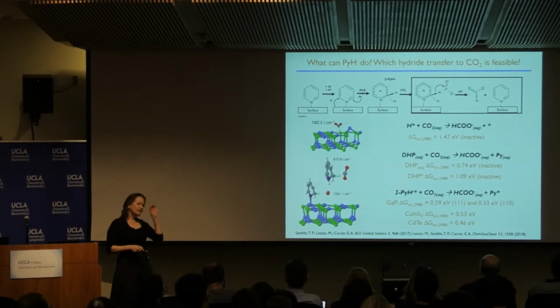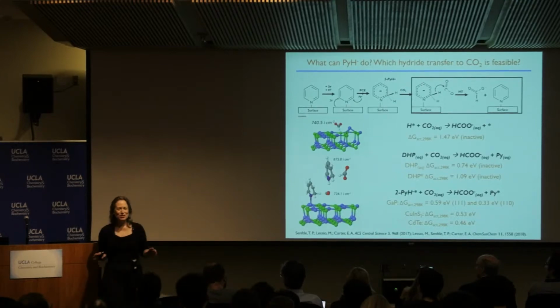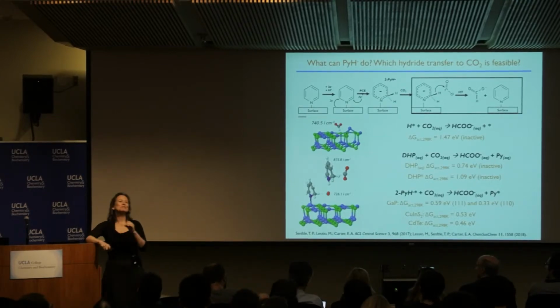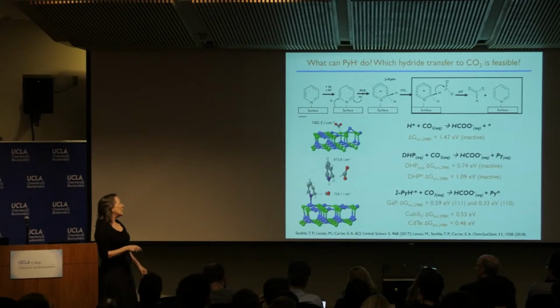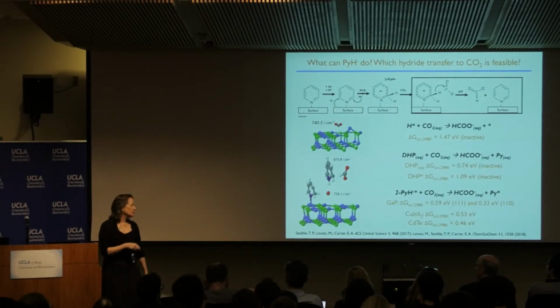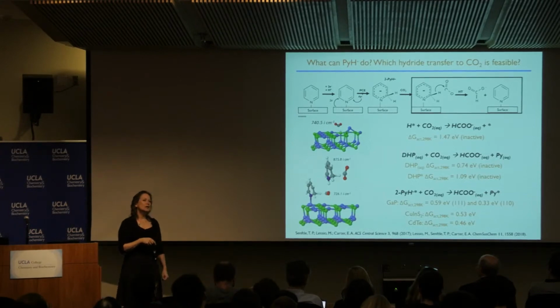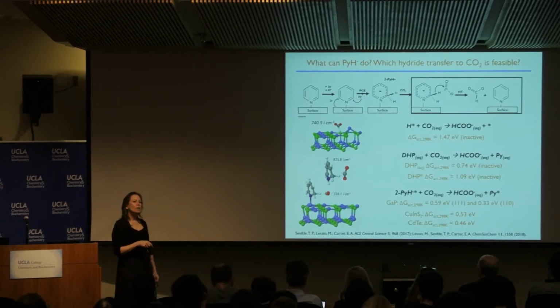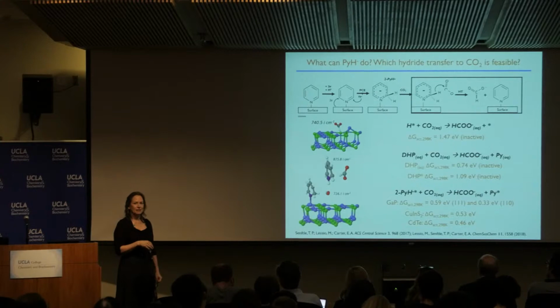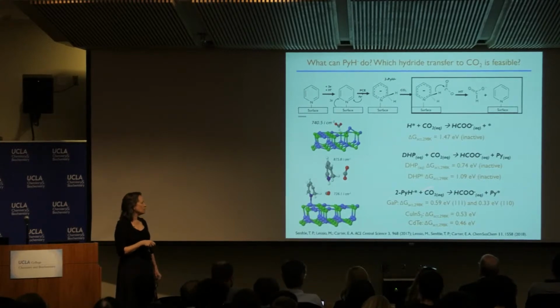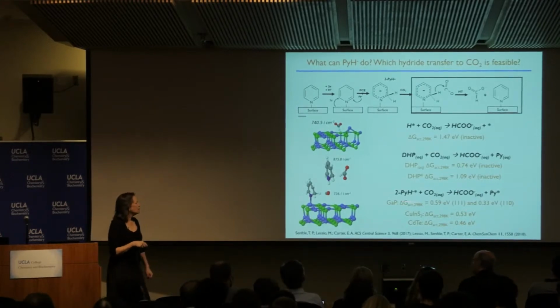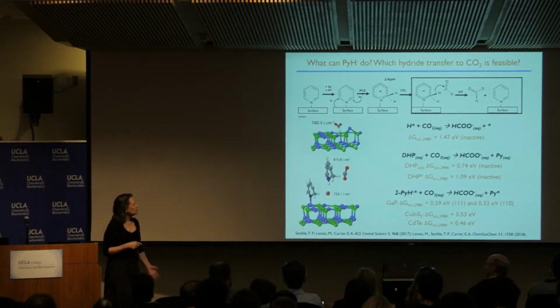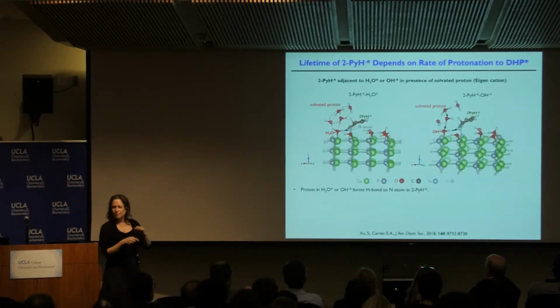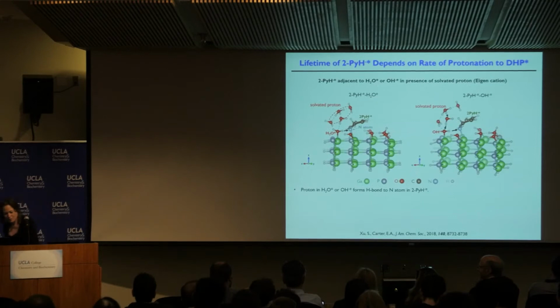And the beauty of that is that Andrew Bocarsly has frustratingly unpublished data. It's in a PhD thesis. We've been trying to get him to write it up with us. But the fact is that what they showed is that if you etch the gallium phosphide 111 crystal, you make facets of the 110, and the rate increases dramatically. So this is consistent with that result, and it's the only species, again, that seems to be possible to be making this. I need to check the time.